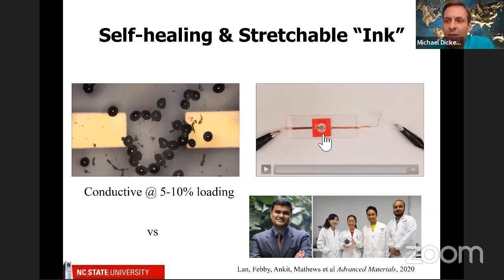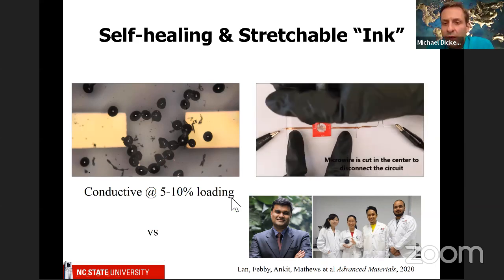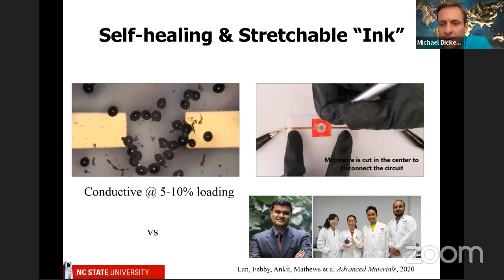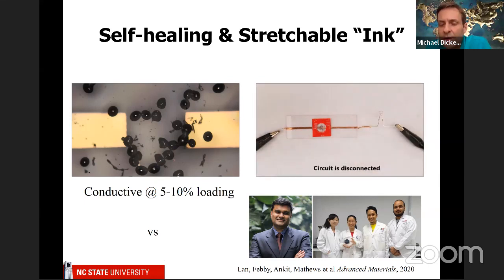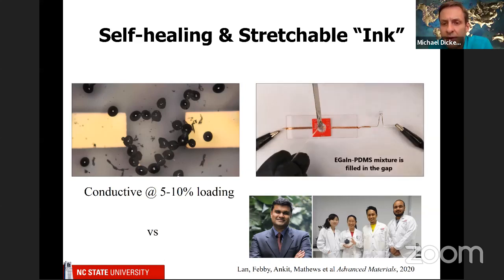you can use this ink. I call it an ink because it's just liquid metal mixed in with silicone. You can make it self-heal a circuit. So here the students came in with a scalpel and completely cut apart their circuit. Now it's insulating, completely resistive, and then they come in with some of this ink and fill it in there.